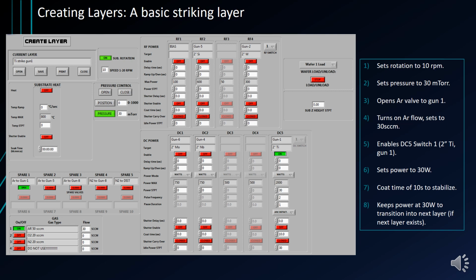Let's take that plasma strike we did manually and turn it into a layer. This is an example of a simple striking layer on a 2-inch titanium target with DC power. Here we have rotation on with a speed of 10 RPM. Pressure control is set to 30 millitorr. Argon is flowing in through gun 1 to the gun containing titanium. The argon flow is on and set to 30 SCCM.